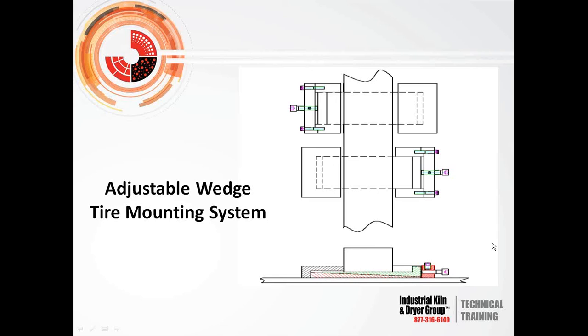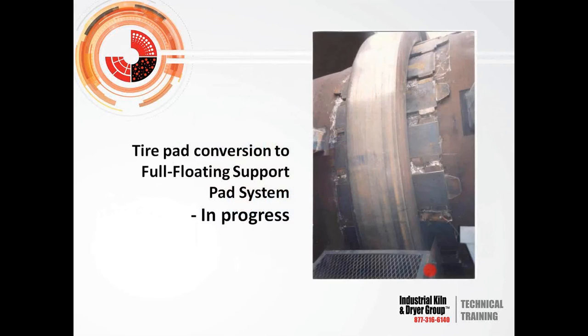Well, basically, we had to come up with a scheme for low temperature, high speed, smaller units, where temperature wasn't really a big issue, but it was still an issue. The upfront cost in a system like this is relatively high, because the wedges shown have to be machined to the diameter, the ID of the tire, their mating surfaces, and the OD of the shell. So essentially, we have to lock these in. On the left-hand side, there's a C-shaped piece that gets welded onto the shell, and on the right-hand side, there's two blocks that get welded onto the shell, just to trap these wedges in so they can't come loose. Then you torque up that bolt, and you can tighten up the tire.